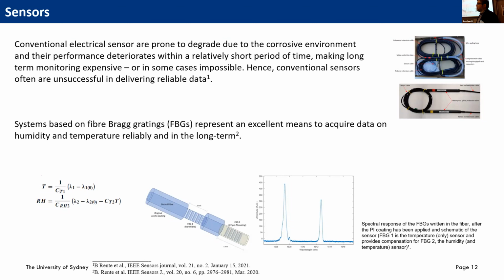There have been fibers developed all around, but our focus is to develop, for example, polymer materials that we can use to coat these optical fibers, for the specific type of condition that we have, because we have a lot of chloride diffusion into concrete and exposure to HCl, hydrochloric acid, and sometimes also sulfuric acid.